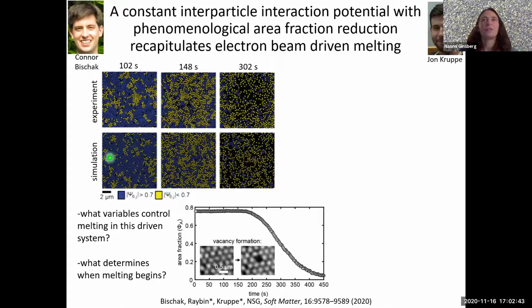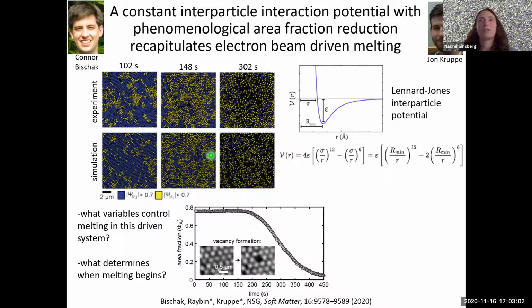And John's simulations recapitulate this behavior really well. So while your initial guess might have been that the dynamics are dominated by something like interparticle Coulomb repulsion, the simulations required not only repulsion, but also a weaker long-range attraction, which is captured in a 6-12 or Lennard-Jones interparticle potential. And so we really do need this attractive force as well. We can't just use, say, a hard sphere model like one might use for many other colloidal systems.